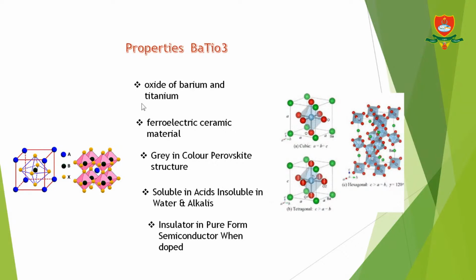Properties of barium titanate. Barium titanate is an oxide of barium and titanium. It is a ferroelectric ceramic material with a photorefractive effect and piezoelectric effect. The powder appears white to gray in color and has a perovskite structure. It is soluble in many acids such as sulfuric, hydrochloric, and hydrofluoric acids, but it is insoluble in alkalis and water. In pure form, it is an electrical insulator, but when it is doped with a small amount of metal such as scandium, yttrium, samarium, etc., it becomes semiconducting. As a semiconductor, it exhibits positive temperature coefficient of resistivity properties in the polycrystalline form.